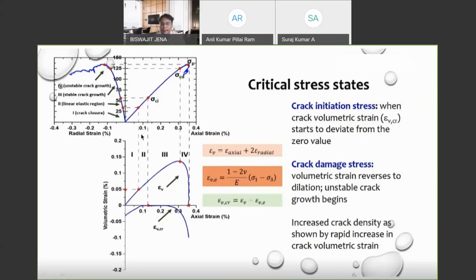Now, if you look at that point where the crack volumetric strain tends to deviate from 0, and if you take it all the way up, you will get what is called the crack initiation stress, which is basically your end of linear elastic region. Now, what happens? Normally, you do this all very randomly. You take the slope, you say that slope has kind of changed, and then you take it. In ultra high performance concrete, you cannot do that because the linear elastic range is much higher because of the very high strength of the material. So you have to actually have this kind of transformation to understand where the crack initiation starts.